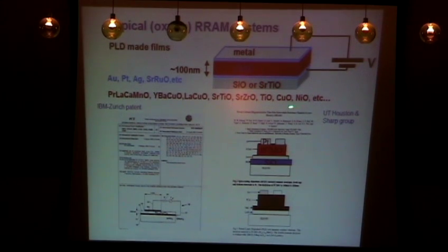So you can go from very simple binary structures like nickel oxide, copper oxide, or titanium oxide that we saw quite a bit yesterday, and increase the complexity up to multi-component perovskite systems like praseodymium lanthanum calcium manganese oxide, which is one of these famous manganite systems. Also, you can use the cuprates. So a very wide variety of systems can be used. This comes clearly as a big surprise.